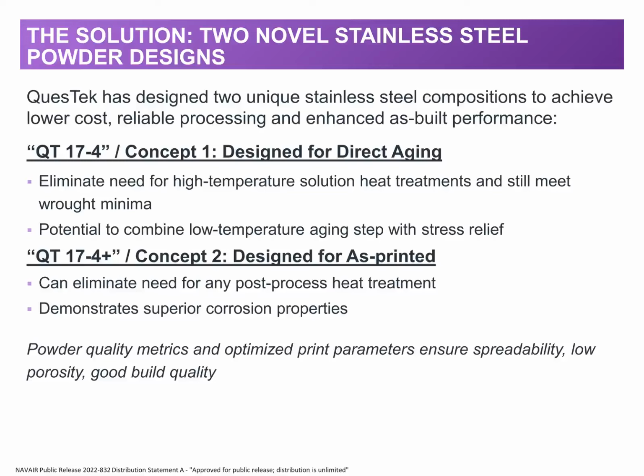QuesTek was able to design not one, but two novel alloys to support the program. Each meets the properties of wrought 17-4 and has the same corrosion resistance. The first one was designed for direct aging. So once an alloy is printed into a component, only a minor low temperature age is required for the component to meet both mechanical and corrosion resistance of wrought 17-4. The second alloy, QT 17-4 Plus, was designed to be used as printed, eliminating all post-processing thermal treatments. This alloy also meets the wrought properties of 17-4 as well as demonstrates superior corrosion properties.